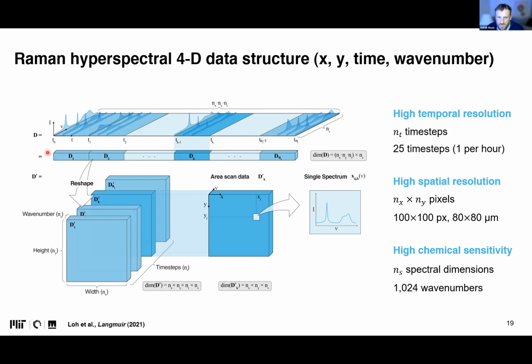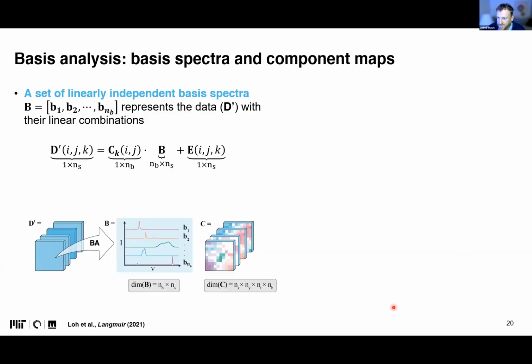So we can do time-dependent measurements. It's a 4D data structure: X, Y for space, time, and wave number is another dimension. And so we can get a lot of information. In general, we collect quite quickly, at about 300 milliseconds for each of these spectra. This allows you to go really fast and get hundreds of thousands of spectra, which is really valuable for statistical purposes.